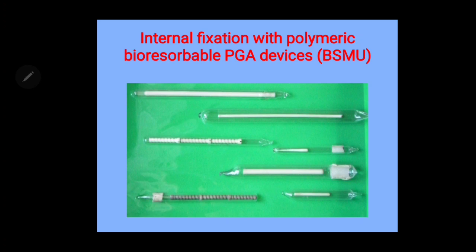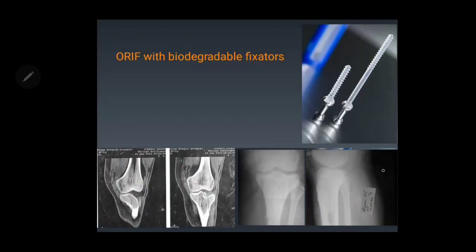We're talking about small devices like small conical pins. Usually 6 months is needed for their total bioresorption. For big devices, for screws, 2.5, 3 years are usually needed for their biodegradation. We also have some biodegradable devices of a new generation already. These are PGA, PLA copolymers, and they are presented in our market by a biotech company.